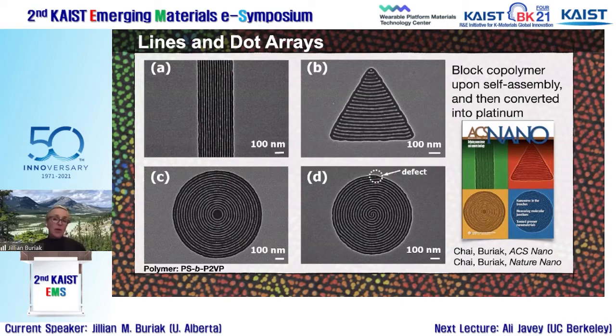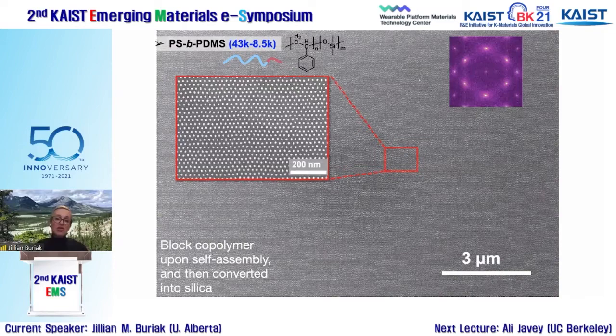So I'm going to go now to the block copolymer that I had mentioned earlier. So this is the polystyrene polydimethylsiloxane. And so this one is forming, in this case, a very large two-dimensional crystal on a piece of silicon. And so you can see this is giving me hexagonal dots. Now the silicon, which is part, of course, of the silica dots, comes from the PDMS block itself. So when we do spontaneous self-assembly, forming that monolayer, in this case forming hexagonal dots, we then do that simple plasma step that I had described, and the PDMS block is spontaneously transformed into the SiOx, the silica block, and forms these dots.